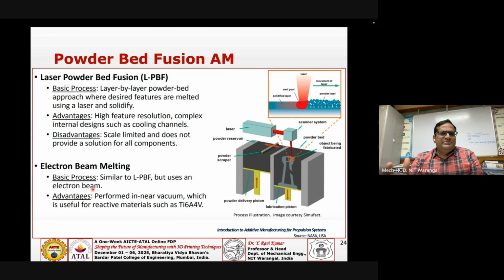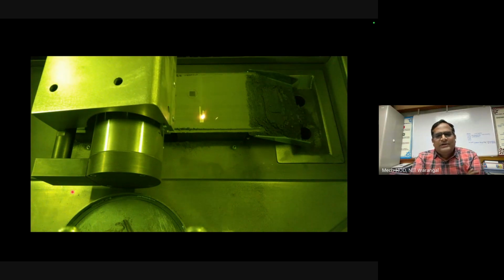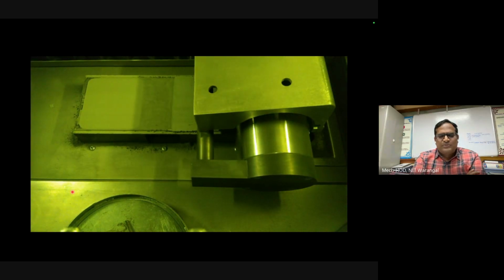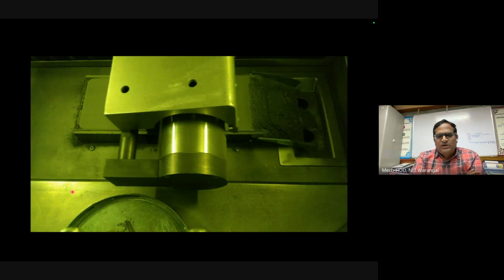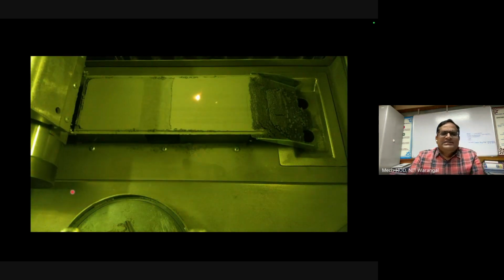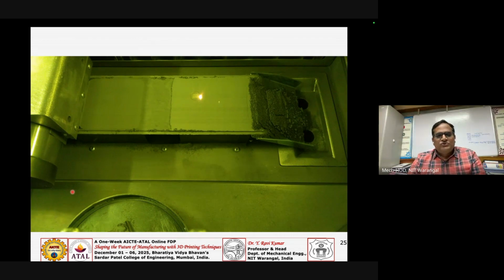And powder bed and the electron beam, these are the two major metal processes which we are talking about. And this is one small video from our lab. This is a powder bed based metal 3D printer or AM machine, where you can see the laser is melting the powder particles, and the powder particles could be on the order of 25 to 30 micron size, and your laser will be melting the powder particles and you have a loose powder around that. Then again, you have the next layer, the roller will spread onto the previous layer, and your process will go on. This is the typical powder bed based laser energy source where you can use.